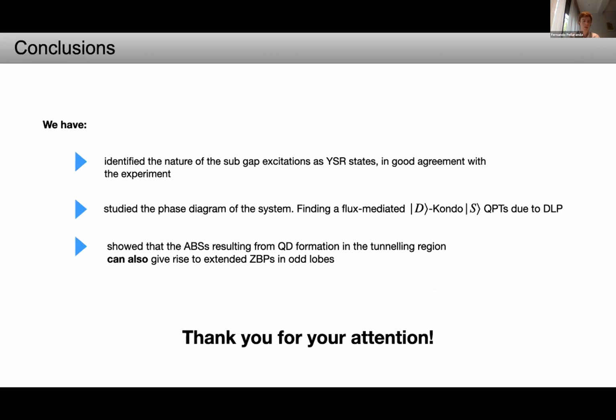So to conclude, we have identified the nature of the subgap excitations as Andreev bound states, which is in good agreement with the experiment. We have also studied the phase diagram of the system, and we have found this flux-mediated doublet to Kondo singlet quantum phase transition induced by the destructive Little-Parks effect. And finally, we have also shown that Andreev bound states, which result from this quantum dot formation in the tunneling region, can also give rise to extended zero bias peaks in odd lobes. So with that, I conclude. Thank you for your attention.